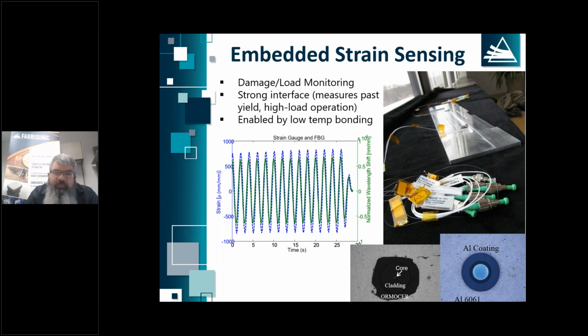On the bottom right, we're showing that ability again of ultrasound to flow metal around a solid metal part. So again, these are fibers on the order of about 150 microns, and we've flowed aluminum all the way around them. The fiber on the left is a glass fiber coated in aluminum. The one on the right is a glass fiber coated in a polymer. So that polymer moved around a little bit, but we were still able to extrude metal and get good interaction between the sensor and the matrix, which is important for getting good data. We find that we can typically hold good high quality data till 2 or 3% past yield of the underlying base material. So you can get data past yield, but certainly there are limits.